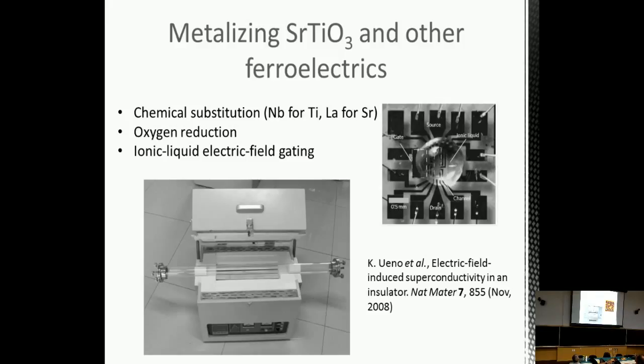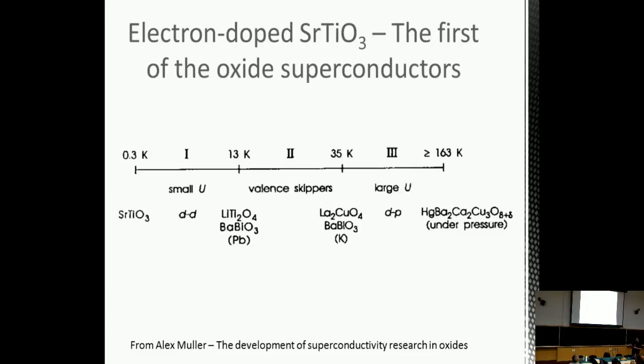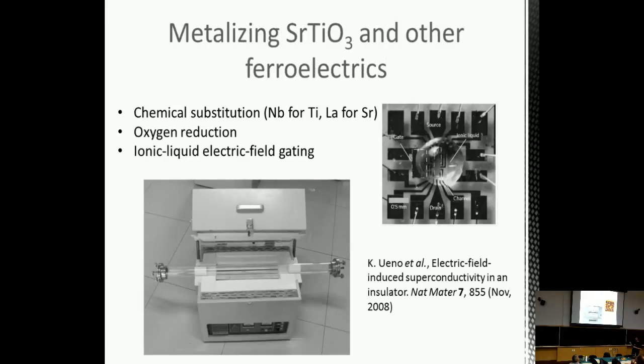Another way you can do it is using ionic liquid gating. So just pure strontium titanate and then electric field injection of carriers, or perhaps electric field subtraction of oxygen atoms, causes the sample to become metallic. And in both cases, the ionic liquid gated version and the bulk samples actually become superconducting at low temperatures.